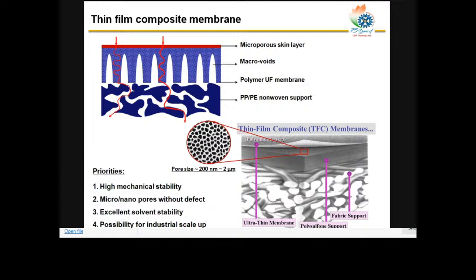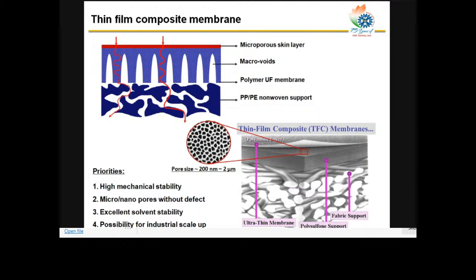If you see on your top left, this cartoon is indicating that the lower part is a non-woven support. And then you have an ultrafiltration membrane on top of that. And finally there is a microporous skin layer. This thin layer is basically the separation layer, which is actually doing the job of separation.